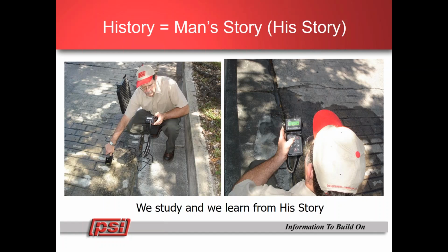History is man's story. We study, we learn from his story, his success, and his trials. In this picture, I was using an impact echo device to try and determine the thicknesses of the street, and I had a lot of confusing data because of the thickness of the pavement, the thickness of the overlying very dense concrete, but by using the relative thickness data and the relative maximum thickness data, we were able to select our core locations to verify what we assumed to be the good range of the thickness of this street.